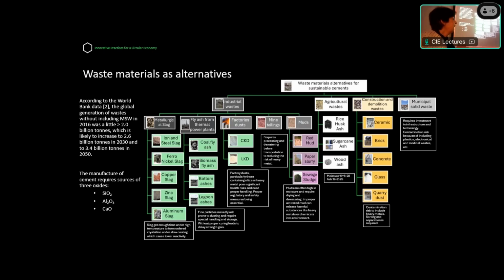The second group are ashes from power plants. So we have coal fly ash, biomass, bottom ash, lagoon ashes, and these materials are inherently fine. So it needs special attention to handling and storage of these materials. And also, for gaining strength when they are used as binder in concrete, if they are cured at ambient temperature and we don't apply a special curing to them, possibly strength gain is delayed.